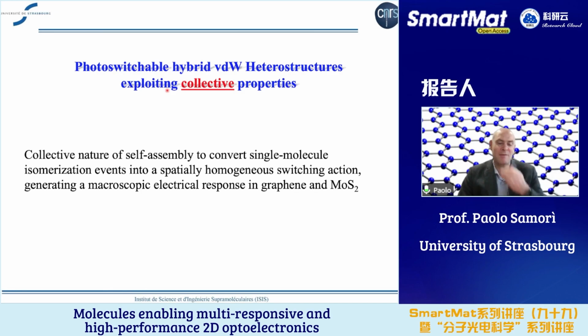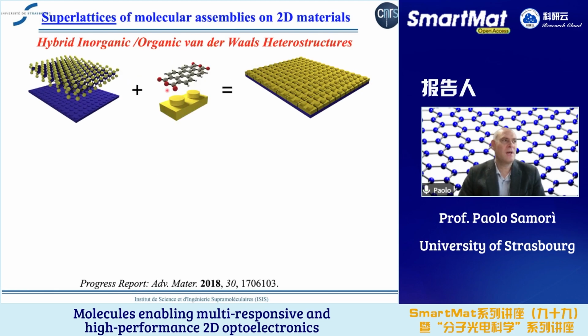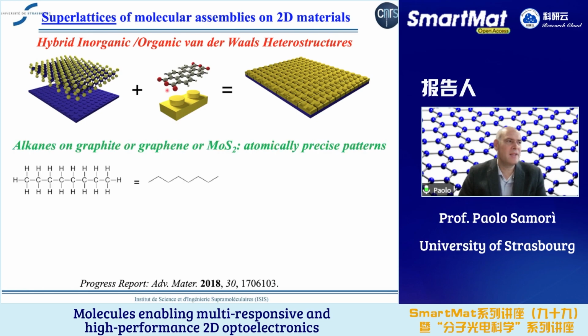And so we exploit the collective nature of self-assembly to convert the light-induced change at the single molecule level into a macroscopic change of the properties of the graphene or MoS2. So you start from the 2D materials, that is your scaffold on the bottom, and you arrange these small bricks, and these bricks are nothing else than pieces of Lego that are switchable.